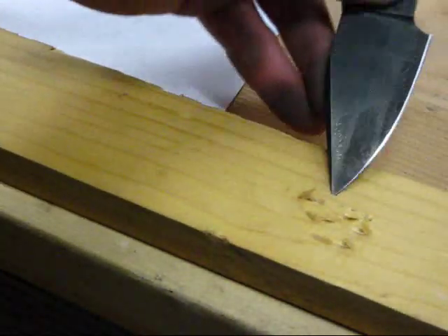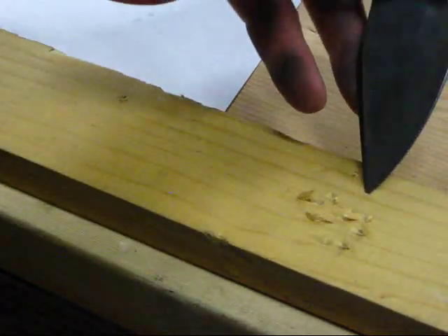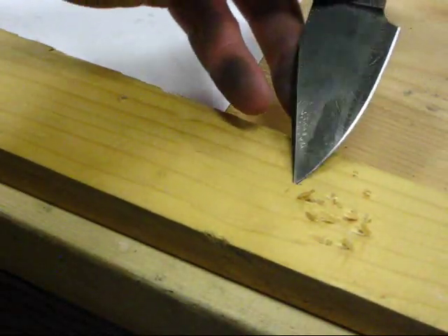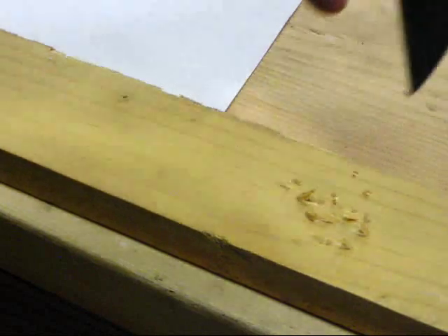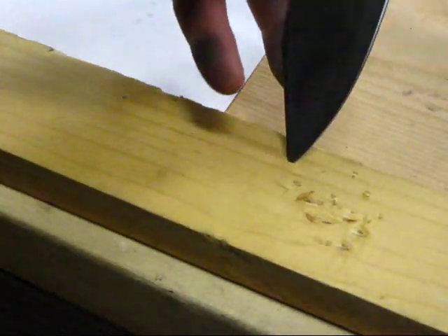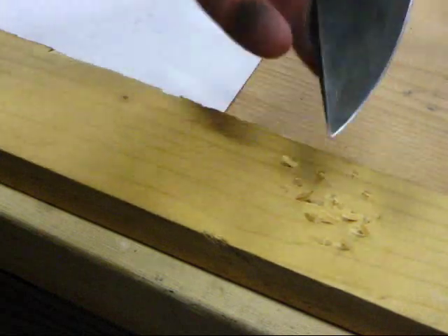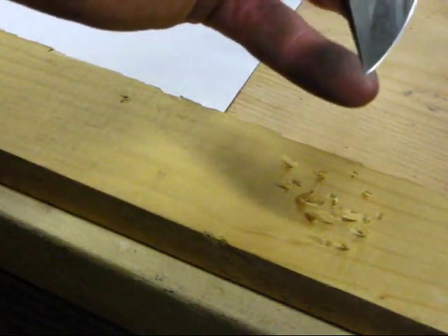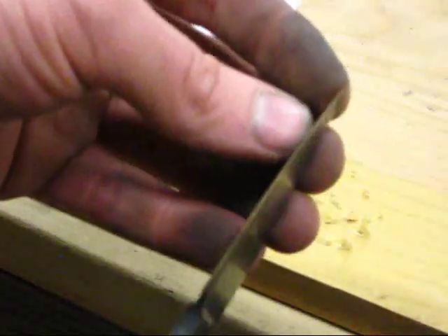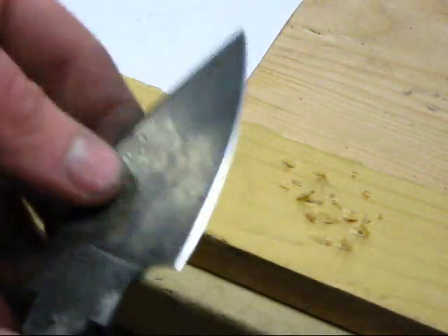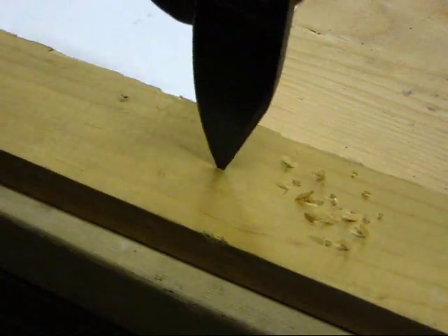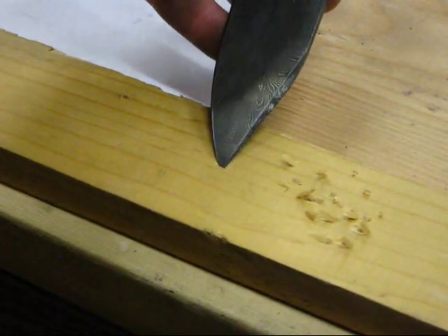I usually go a little bit more conservatively at first, just because if the edge is too hard, it will typically break right away, and I would rather chip off a little chunk of the tip than a big one. But after I feel it out initially, then I'll go a little bit more aggressive with it. Now what I'm going to do is I'm going to look at the tip and make sure that it hasn't folded on me, that it's still nice and straight, and from what I can tell, everything still looks good. So I would definitely say that this blade passes the pine board test.